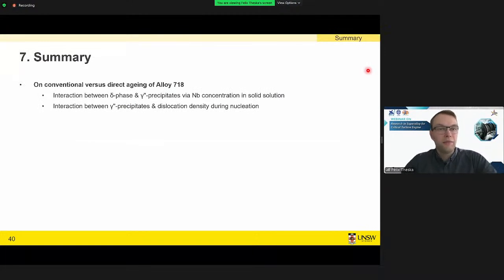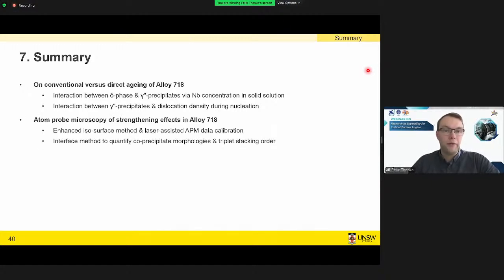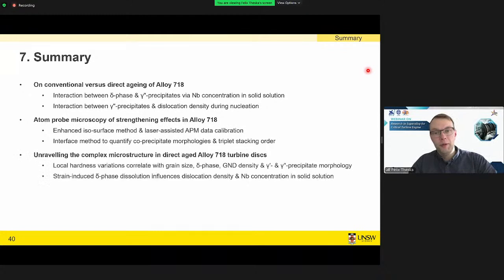All right, now let me move on to the summary, just to wrap up what we have observed. In the first study, we have observed the interaction between the delta phase and gamma double prime precipitates through the niobium concentration. We also have observed that the dislocation density plays a very important role. With our Atomprobe microscopy toolbox, we could find ways to calibrate large data sets and quantify our co-precipitate morphologies, which we then can use to quantify data in turbine disks.